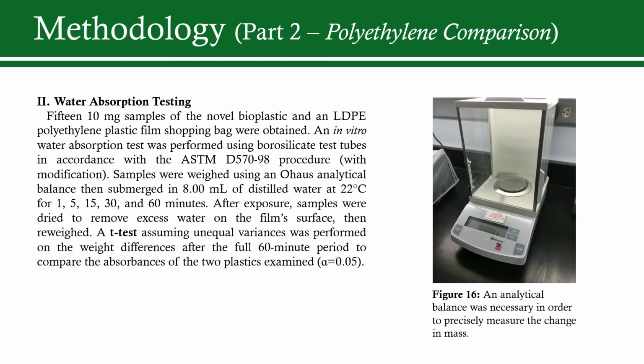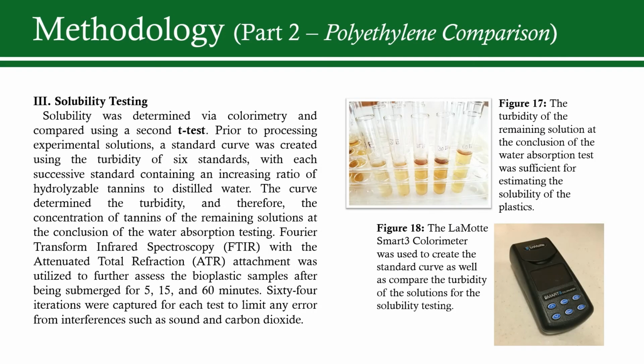Next, water absorption, in addition to solubility, was calculated. 15 10 mg samples of both the bioplastic and polyethylene film were submerged in distilled water for a period of either 1, 5, 15, 30, or 60 minutes. Samples were gently dried to remove any water on the surface and reweighed in an analytical balance. The remaining solution was then transferred to glass sample vials in order to determine turbidity and therefore solubility by comparing the turbidity to that of a solution containing one completely dissolved strip.